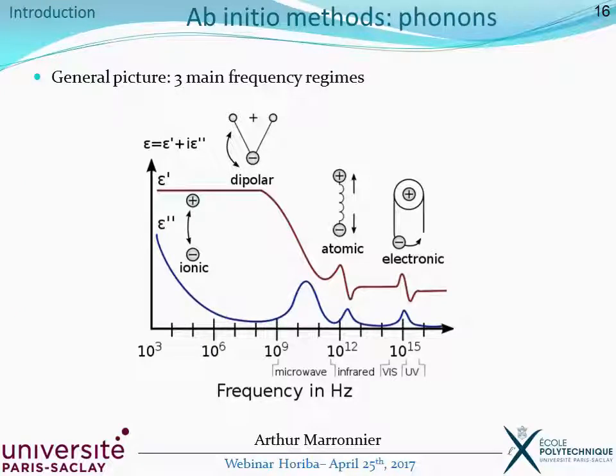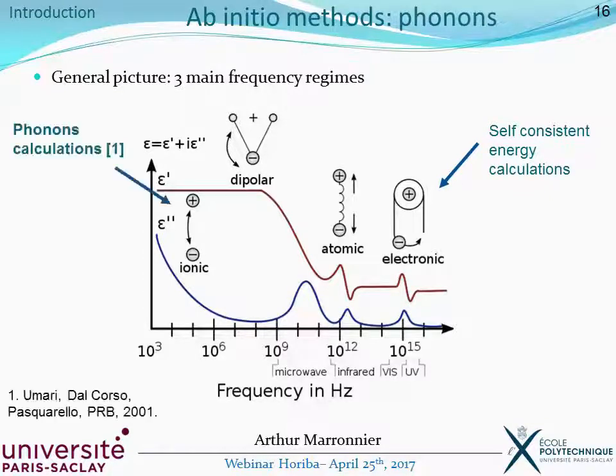Now you have to remember that the dielectric constant depends on the frequency. You have different regimes. In the high frequency regime, you only need to take into account the electronic contributions. But when you go lower in frequency, you have to add the atomic and the dipolar contributions, making epsilon go higher for its real part. Well, the high frequency value of epsilon can be directly derived from self-consistent energy calculations, so this is quite easy. But for the dipolar contributions, when you go to a static epsilon at low frequency, this is trickier, and we use the method based on phonon calculations that is detailed in this article here.